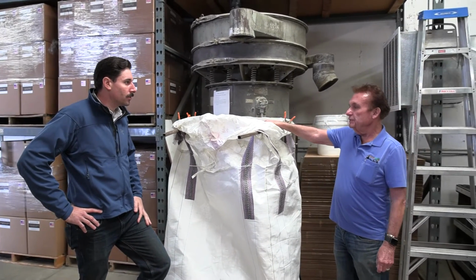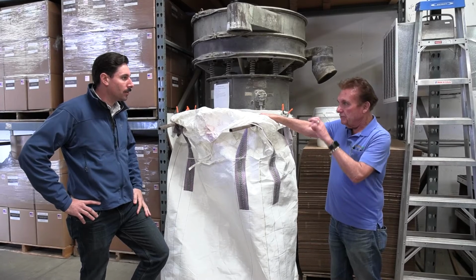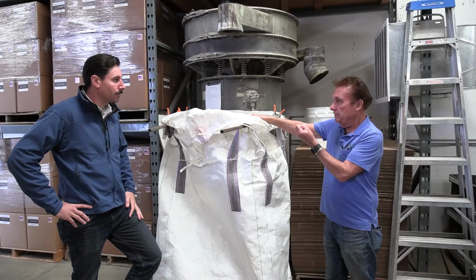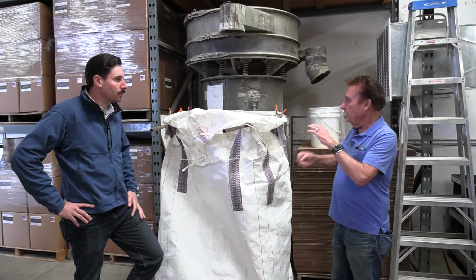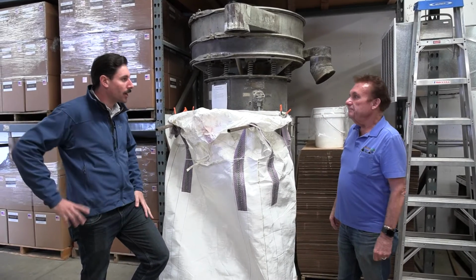It's a zeolite, which is a volcanic rock, and it's like a molecular sieve. It has a lot of surface area, and that's why we can get around 5 to 6% permanganate in there, which is the active ingredient. That's what you mean by impregnating the zeolite. Right. That's what we do in the mixer, and then we bring it in here and shake it, and then we make our products.